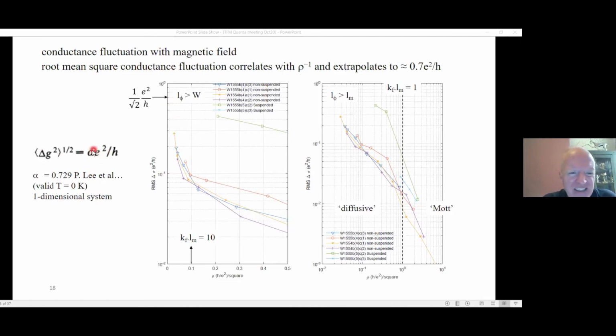The prefactor there, alpha, is about 1, but for a 1D system, it's 1 over root 2. It's not the fact that you're measuring a root mean square value of a quantity, hence the quantity is root 2 times the value. It's because the system is behaving as 1D. And I think what's happening here is that the phase coherence length is becoming wider than the width of the device.